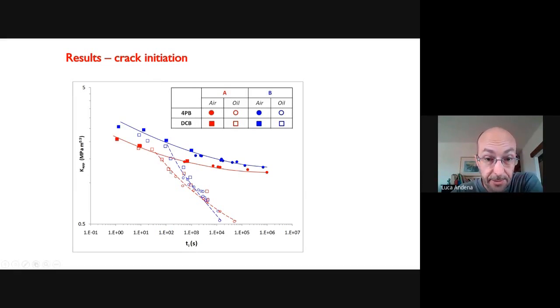And also, you see that the effect of the environment is huge because at a given K value, you can have orders of magnitude difference in initiation time. Typical values, of course, are low here because you don't expect failure of products in a few hours. And you can identify a critical interaction time. Well, if the load is too high, failure will occur before the medium has time to diffuse within the polymer and play a role.